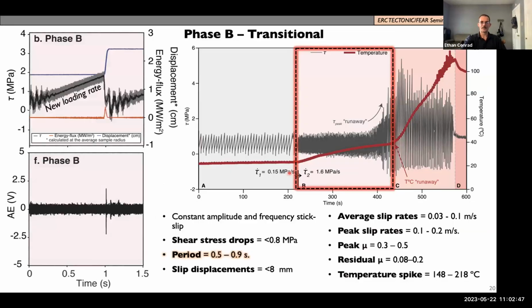Thank you. Yeah, so we were just jumping into phase B. So this is after we increased the loading rate. And with the new loading rate, obviously the slope of the shear stress curve is going to increase because we're loading more rapidly. With the friction drop, we have slightly higher displacement, slightly more energy flux to the surface. There's a little more action and more information in the acoustic emissions spectrum here. And importantly, the period decreases. So we really increase the frequency of events, and this leads towards a building of the fault temperature, because between events, there's less time for the heat to dissipate. And so there's this memory of the heat from the previous event, and you're kind of building onto that.